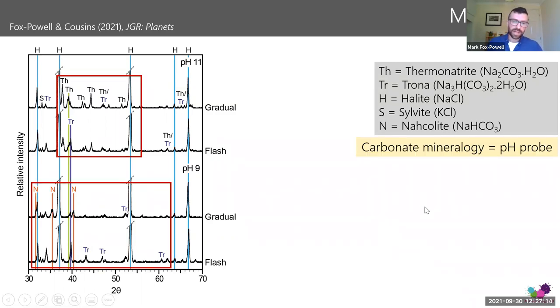Remember that we predicted through the thermodynamic approach that we should see differences in the carbonate mineralogy, and indeed we do. We see that thermonatrite, this sodium carbonate mineral, is dominating in the pH 11 regime, whereas we have nahcolite and this trona phase here forming in the pH 9 regime. This is an indication that if we can get mineralogical information from plume particles and the crystalline salts that exist there, we may be able to use this as an independent pH probe.